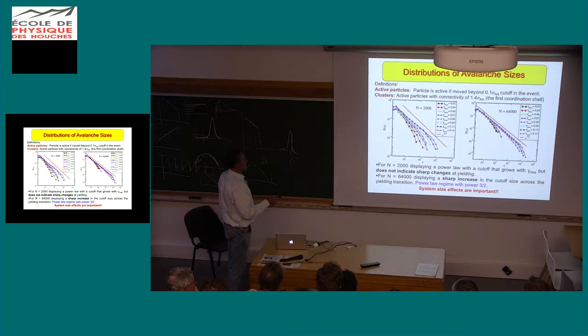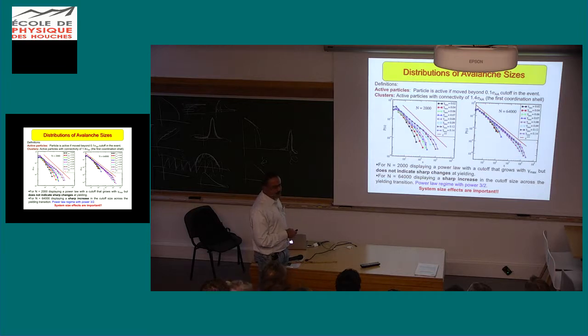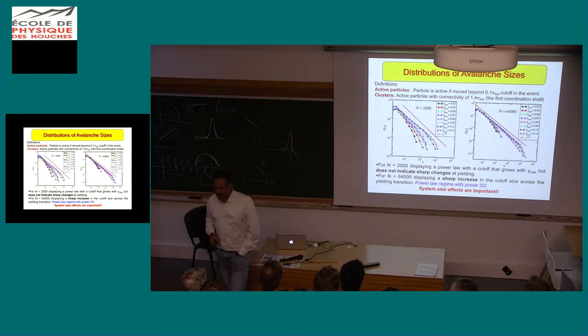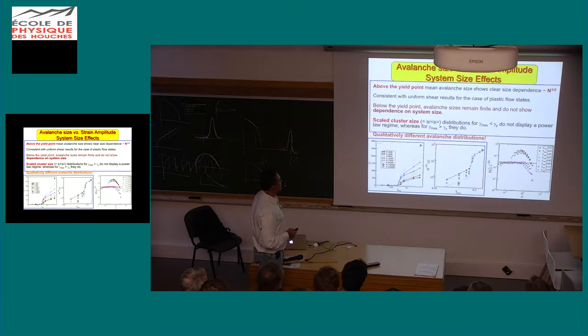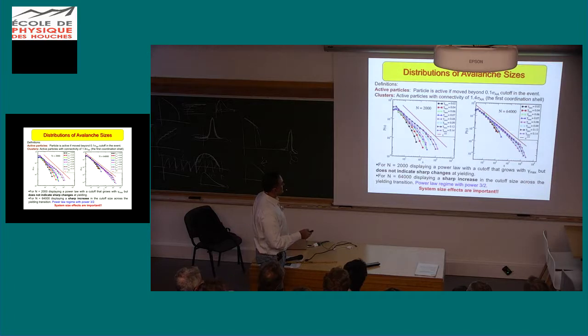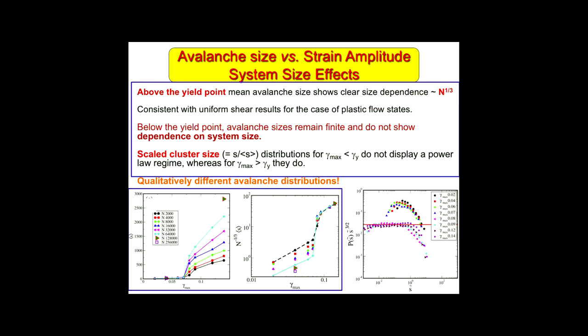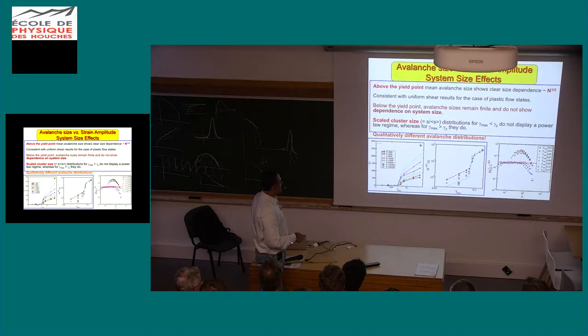For a small system size, as we increase the amplitude of strain, the distributions look familiar, but nothing significant happens when we cross the threshold strain. On the other hand, when we look at a sufficiently large system, we begin to find that the avalanche distributions fall into two significantly distinguishable categories, and we can look at how the mean sizes of these different cases behave as a function of the strain amplitude, and also as a function of system size. I'll come to that in a minute.